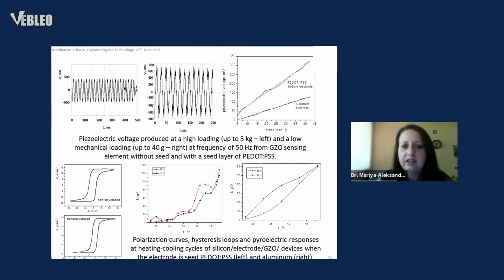So as you can see, the signal before and after the seed layer introduction, and comparison in a linear plot according to the mass loading. The linearity is not strongly affected, but at the same time, even at small mass loading of a few grams per square millimeter, it is almost double, and at the largest mass loading almost triple, the increase of the sensing reaction. And here is presented the polarizing ability, the hysteresis loop after nanostructuring. It is narrow. It means a small driving force that causes polarization as compared to the non-structured material, which could be considered as better sensing ability.